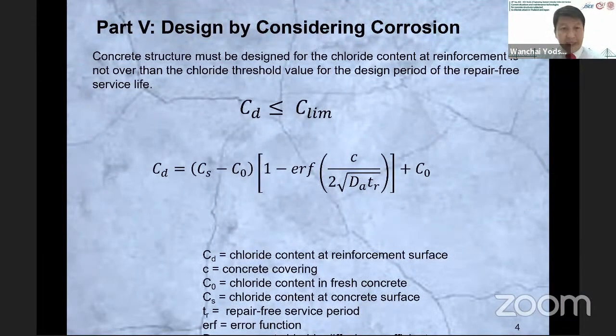The next one is about part five, the design by considering corrosion. Concrete structure must be designed for chloride content at the reinforcement not over the chloride threshold value for the design period of the repair-free service life. It means that the chloride content at the surface has to be lower than the chloride content limitation. And we decide by using the Fick's equation.